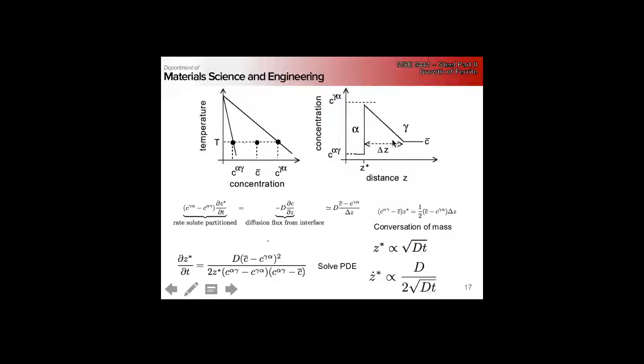So we can model this by saying that the rate at which the solute is being partitioned has to be equal to the diffusion flux from the interface. That means all of the carbon coming out of the ferrite has to go through that interface. It's just a balance, and then this, we give our conservation of mass, and we can combine that with the diffusion equations.